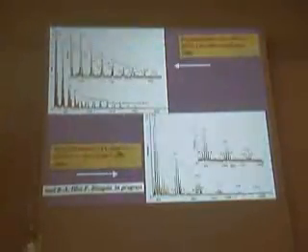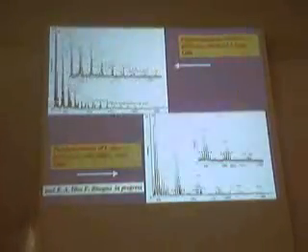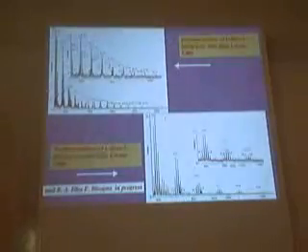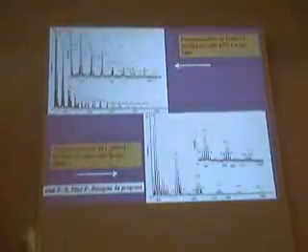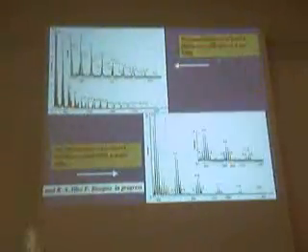And we did it also with L-isoleucine with L-leucine, and D-isoleucine with L-leucine. By labeling one, of course, because they have similar molecular weight, if you take, let's say, the L with D and the L with L, you get very different distributions. If you take L with D, D-isoleucine polymerizes separately, L-isoleucine polymerizes separately, as is expressed here in the molecular weight of the system.